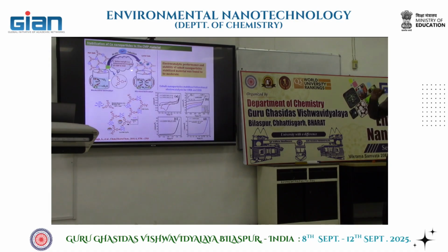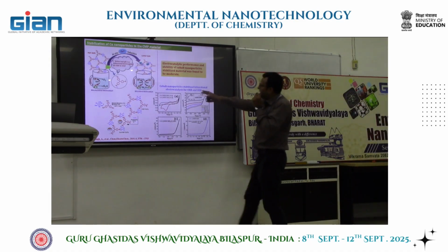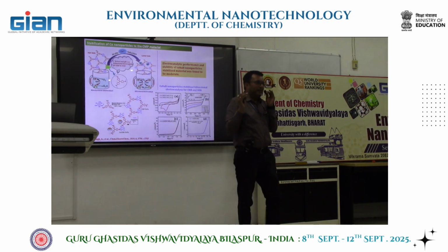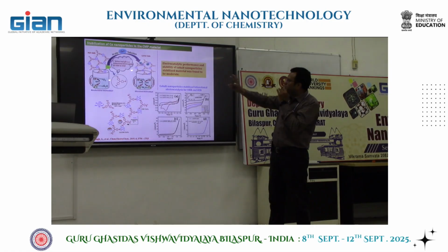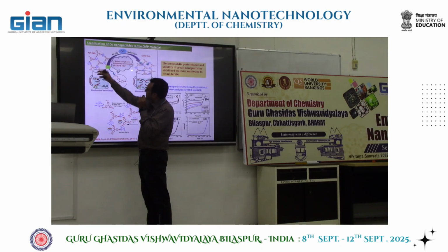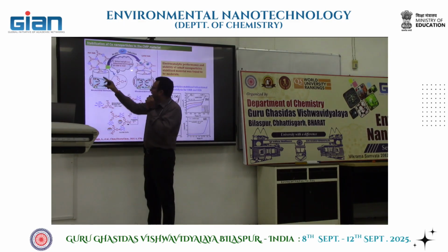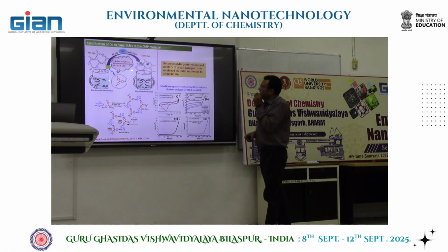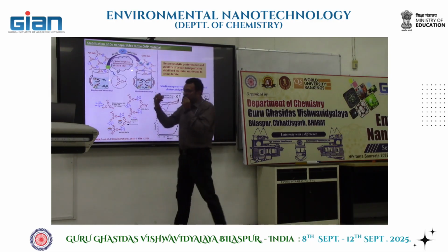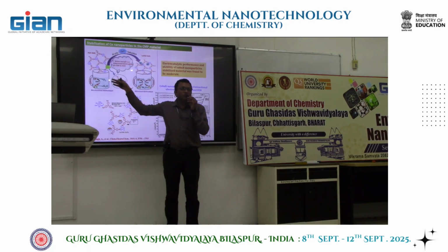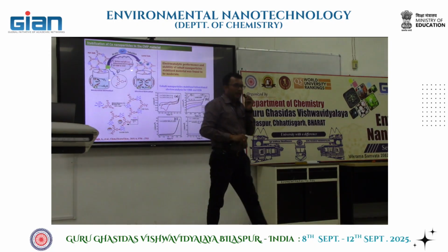So in this one, using phloroglucinol and again triphenylamine as a precursor, we got again a redox active polymer, where you can see that phloroglucinol is like an electron acceptor and triphenylamine remains as an electron donor. Then, as I was telling, this material itself is ORR active, but not OER.